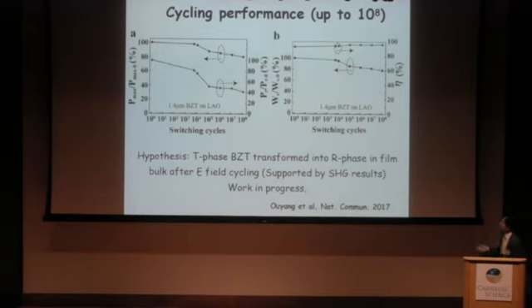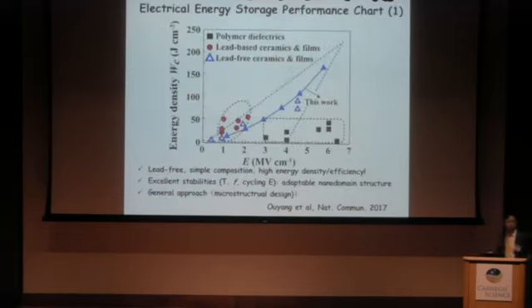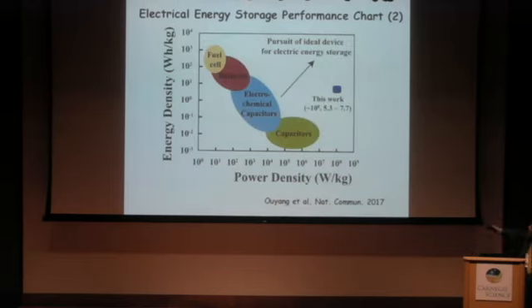And we have some nice work actually in progress, trying to explain the cycling performance, comparing the performance of some fresh and some fatigue capacitors. And here just put you in the perspective how this compares with some of the top performers. Dielectric polymer, they're good in dielectric strength, but they're low in dielectric constant. That's why they're in this corner. And some of the lead-based ceramic, the high dielectric constant, but they cannot induce high voltage. But this blue line is my BZT thin film capacitors. It's good both in dielectric constant and the dielectric strength. And if you put in this famous chart, you're always looking for electric device with both high energy density and high power density, and this is where this work is at.